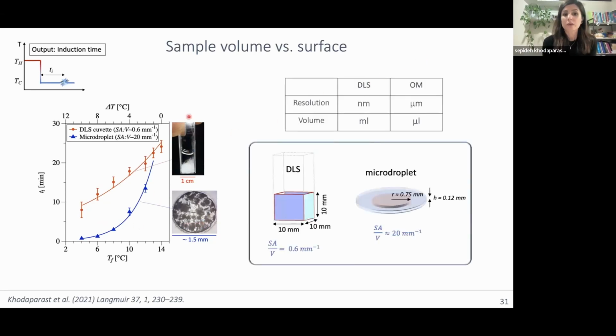The first technique, the one in red, has much higher detection resolution, in nanometers, compared to optical microscopy, which is micrometers. And it's a much larger volume, which means that if you have homogeneous nucleation of crystals in the bulk, with this larger volume and smaller resolution, you should detect crystals much faster than optical microscopy.